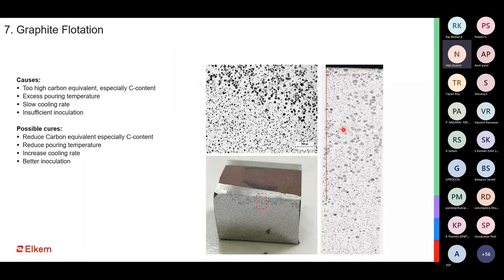So, you know, we saw exploded graphite, we saw chunky graphite, and then the third one is graphite flotation. The cause for all these three kinds of graphite structures is mostly the same. The most common aspect is the high carbon equivalent, especially the carbon content in the casting. So when you have a higher carbon equivalent for the given section, you can get exploded, you can get chunky, you can also have graphite flotation issues.